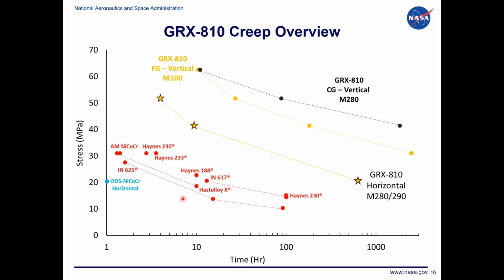And so this is an updated creep overview from the one that you originally saw. Again, it has your conventional superalloys here in the red. Here you can see the nickel cobalt chrome ODS in the horizontal orientation. And then here you can see GRX-810 in the horizontal orientation. Still an order of magnitude or more improved compared to your conventional alloys, and significantly better than our ODS nickel cobalt chrome. But as you use this alloy, be aware there is some creep debit depending on the orientation that you're testing here.